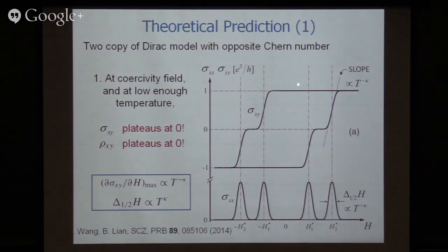Interestingly, you saw previously that as I switch the magnetic domain, the Hall resistance jumps from 1 to -1 in a very abrupt step. But we actually predict theoretically, which remains to be seen experimentally, that between them there's also a 0 conductance plateau.